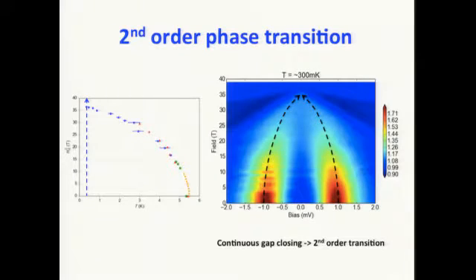And here I show the phase diagram. We perform measurements at this temperature with increasing magnetic field. I show the differential conductance in a contour plot like this. With increasing magnetic field, you can see that the two quasi-particle peaks come in continuously. So it suggests it's actually a second order phase transition.